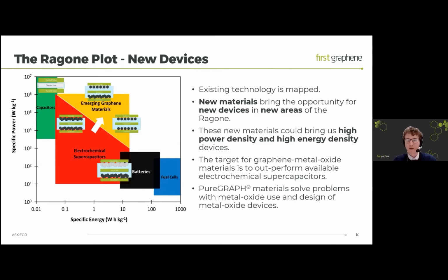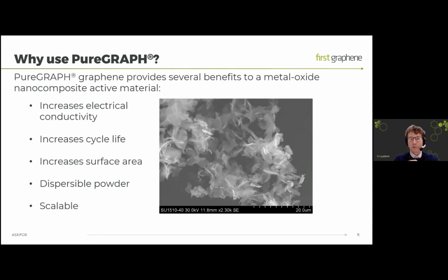And that's why these hybrid materials are so interesting: metal oxides aren't very electrically conductive. And so by depositing these metal oxides onto a graphene substrate, we're able to increase the overall conductivity of the system. Having that intimate contact between the metal oxide and the graphene increases the electrical conductivity. It also synergizes quite well with the graphene, because the metal oxides stop the graphene reagglomerating. Once you've dispersed this and dried it out, it stops the graphene restacking by having those deposited metal oxides on the surface of the graphene.